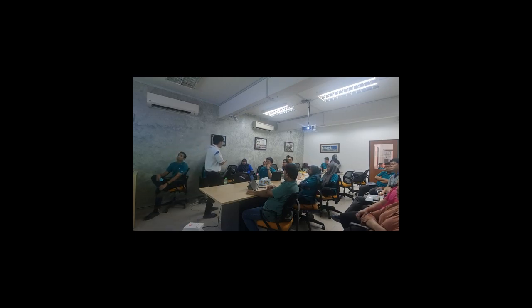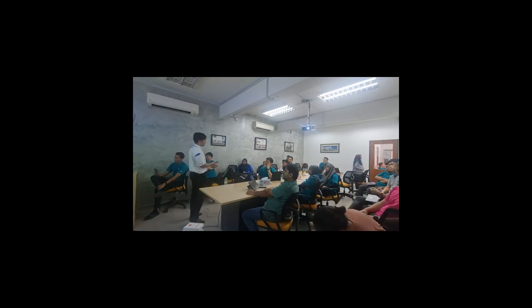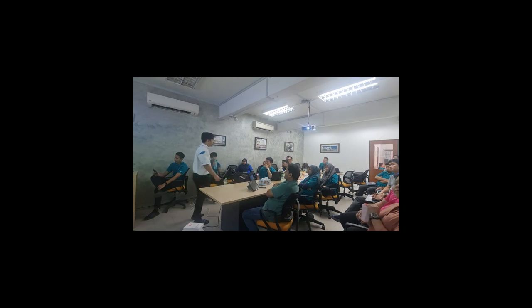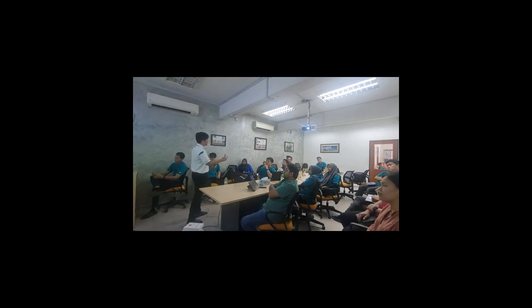Calcium carbonate, you still have to go through processes, and it's not necessarily used only for concrete; it can be used for other purposes. Fly ash, they want to dump it into concrete. Of course, it also has a plus point: it improves the durability of your concrete. But sometimes it depends on the reactivity of your fly ash. Because it's a byproduct, which we can't control, you have to be careful and test yourself. If you see a little difference, you may have to recheck or adjust your mix design a little. Generally the strength is similar to OPC, but fly ash takes more time to gain strength. Maybe not 1 day, maybe 3 days.